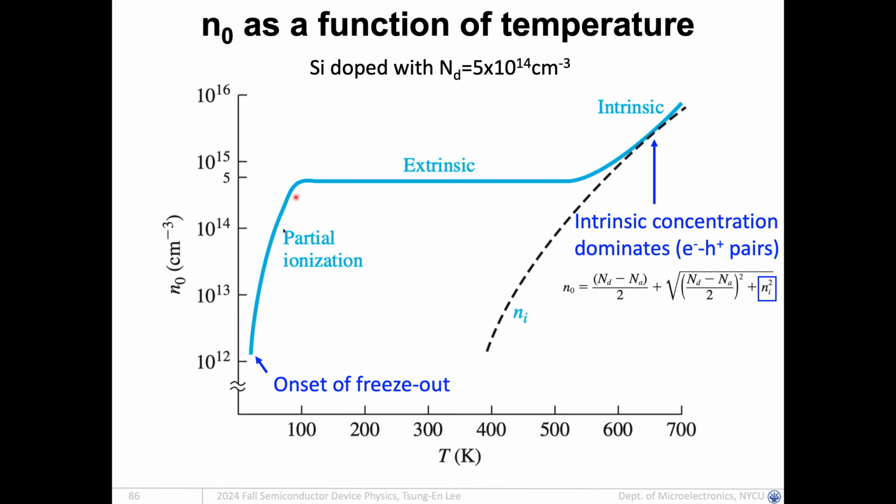And so the carrier concentration will gradually increase. It can easily increase with just a bit of temperature, even lower than room temperature. Around 100K, it can be completely ionized. At that point, the carrier concentration will be almost the same. It is a completely ionized extrinsic semiconductor.